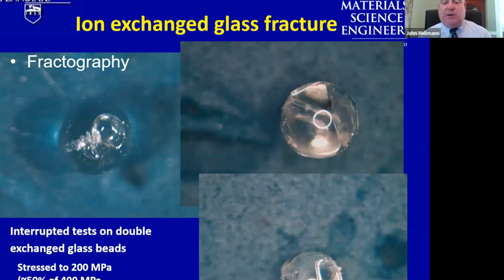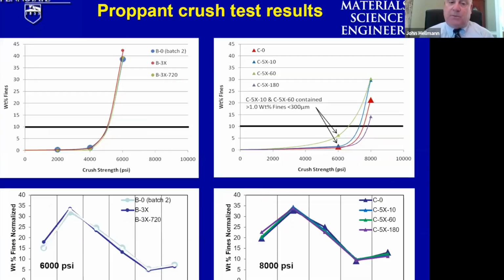This particular bead was stressed to on the order of about half of its characteristic strength, and then fractography was performed. We also employed American Petroleum Institute standard test methodologies to understand how these proppant particles before and after ion exchange performed in crush tests.